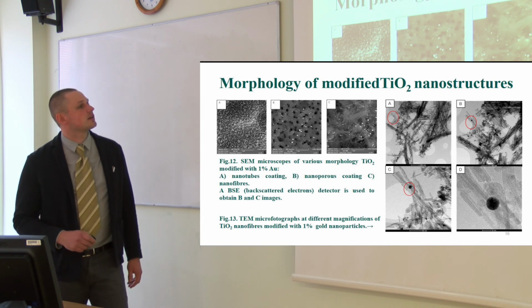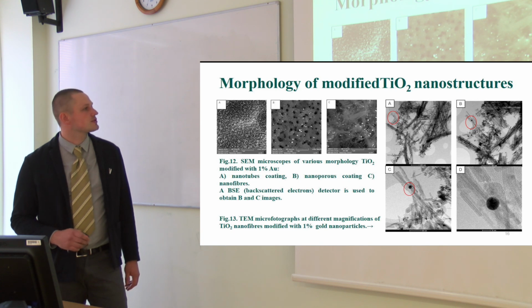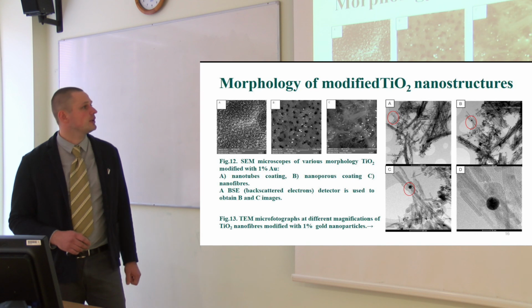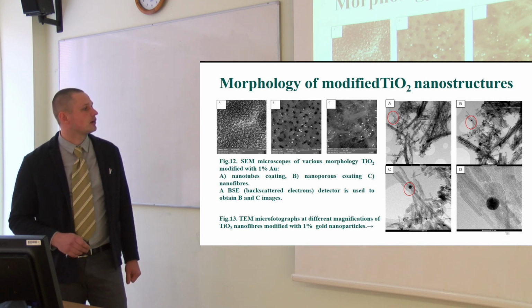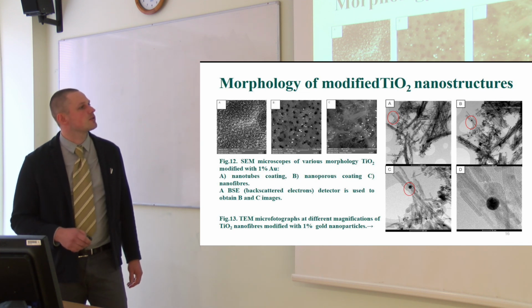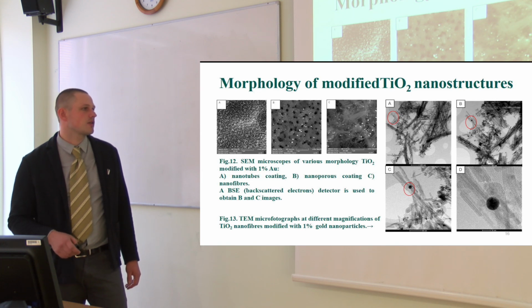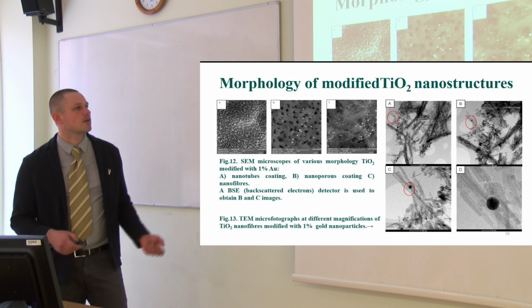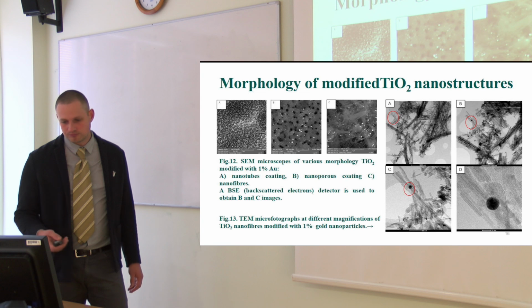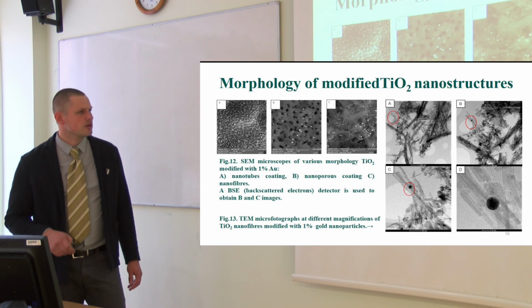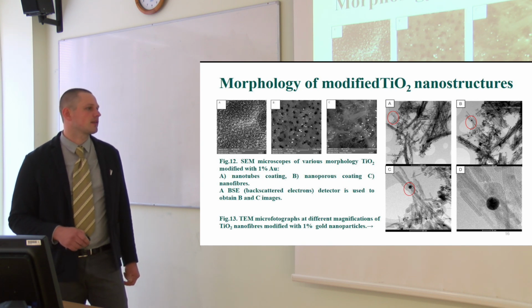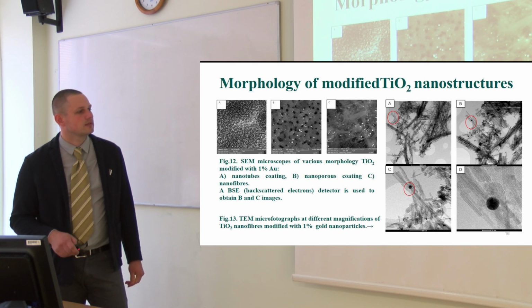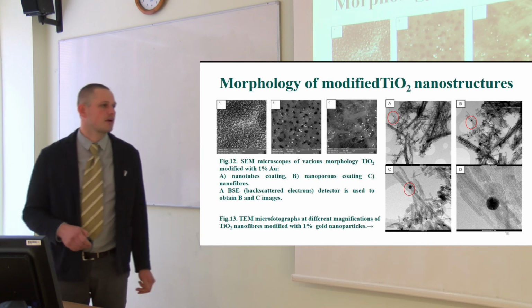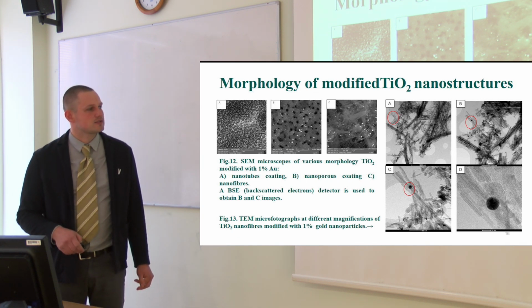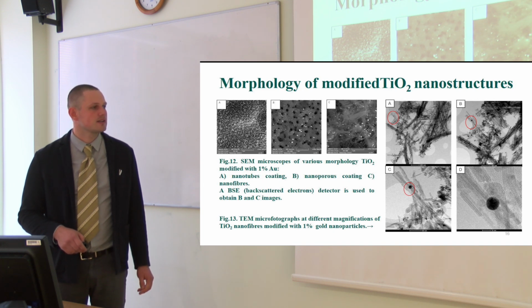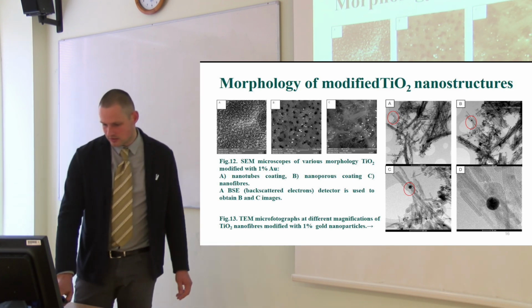So, here are morphologies of our obtained modified titanium dioxide nanostructures. Here you can see nanotube coating. For this sample, it was typical detector used. For these two samples, we were using backscattered electron detector that allows us to see our dopants or modificator particles, so we can see them better. And here you can see one sample modified with 1% of gold nanoparticles. As you can see, gold is in form of some crystals, with crystalline size 10 to 25 nanometers.